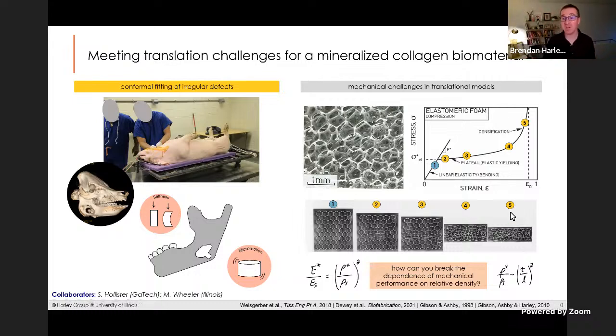So what we want to do is design porous materials to stay in this linear elastic regime, but be as strong as possible. So we want the slope to be as high as possible. The challenge is the mechanical performance of porous materials scales as its relative density, or how much stuff is in it. So if you have a material that is 1% dense or 99% porous, and you make it 2% dense or 98% porous, the math tells us that material that is double the density is now 4 times as strong. So we can make materials that are much stronger by adding more material into our scaffolds.